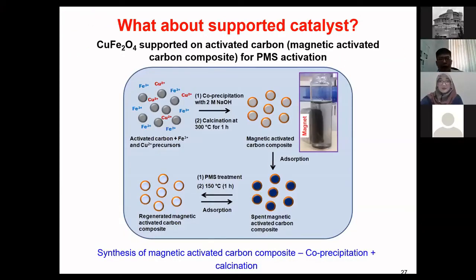At the beginning of the mixed metal oxide, I talked about copper ferrite. So here we also just want to look at whether we can improve copper ferrite if we turn it into a supported catalyst. What we did was we support it with activated carbon. We use activated carbon because it has high surface area, which means you can disperse it very well on the support. Also, this activated carbon has adsorption functionality, which means that you can have synergistic adsorption and oxidation processes together.